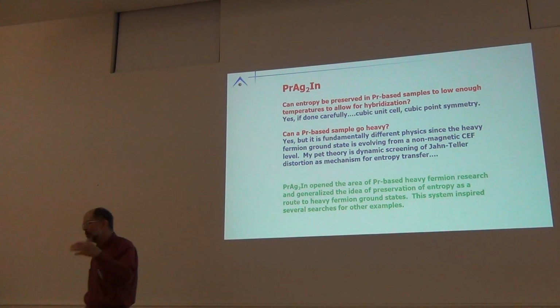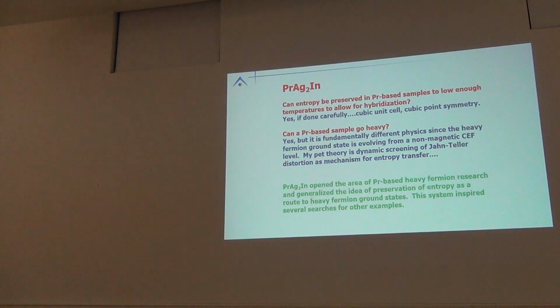If you think of cerium or ytterbium, you have your local moments, and as they're fluctuating, they're being screened by a cloud of electrons. It's sort of this dynamic singlet. This has no moment. Instead, I have a non-Kramers doublet that actually has the possibility of having a Jahn-Teller distortion. Okay? So I think what you're doing is you're dynamically screening this desire to have a structural phase transition. Okay? So, by having this negotiation with nature, we were able to come up with the first clean example of a praseodymium-based heavy fermion.